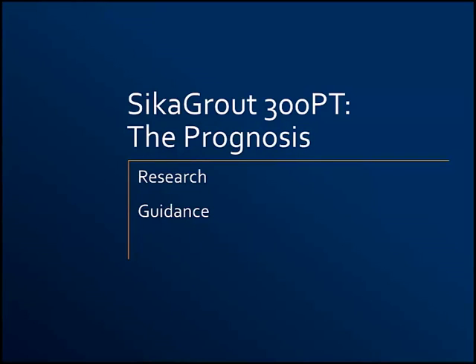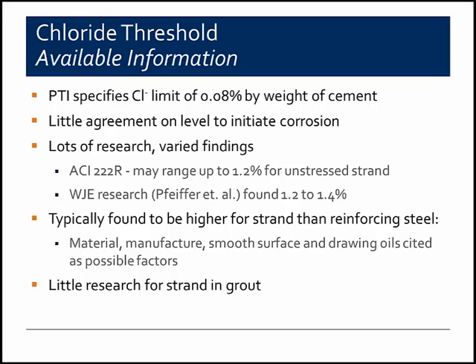So that kind of summarizes the field work, and now we can take a look at some of the research that is ongoing to try and assess the significance of the problem. In terms of the chloride content and the chloride threshold, PTI, as Brian mentioned, specifies a chloride limit of 0.08% by weight of cement. However, there's little agreement on how much chloride it takes to initiate corrosion. There has been a lot of research done, and in general, the findings are all over the board. ACI 222 has reported that the chloride content threshold for unstressed strand may be as high as 1.2%, and WJE has done some research in the area and found similar numbers, maybe even up to 1.4%.